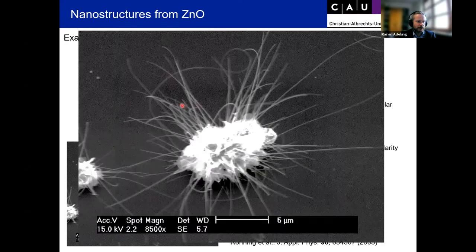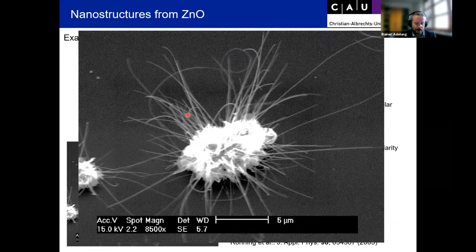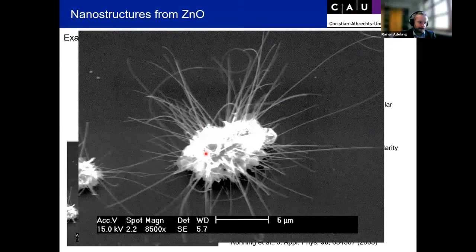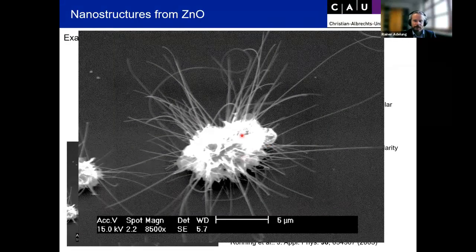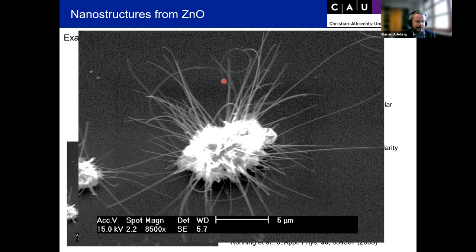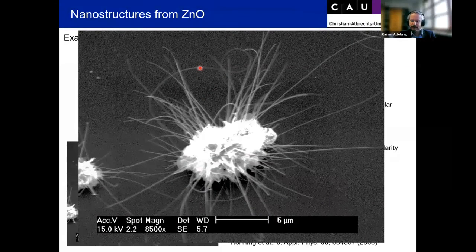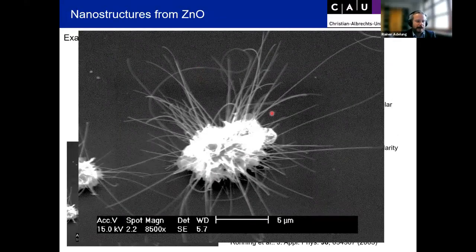This is because the C-axis in this crystal structure grows very rapidly. As soon as you form a layer of zinc, immediately oxygen, if it's around, will settle down due to the high polarity, and then zinc comes and so on — it basically shoots out in the C-axis. Similar to what Professor Mimura was showing, catalyst particles of gold can be placed on a zinc grain. If you heat the whole thing in the oven, you get growth — not of carbon but of zinc — in very thin wire-type structures that are single crystalline but very flexible.